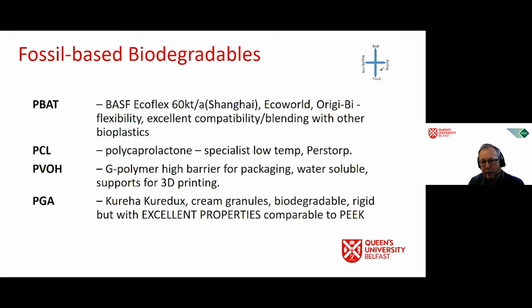So finally, of the four sections, if we look at the fossil-based biodegradables, this is where we use fossil-based materials to produce a biodegradable material. PBAT is probably one of the most well-known, and it is a well-established material. It is a very flexible material, which is used for flexible films, but it also has excellent compatibility with other biomaterials such as PLA, PHA, and thermoplastic starch. One of its typical applications is for compostable caddy bags. There are several suppliers of PBAT, and EcoFlex by BASF is just one of these, and they have a capacity of something like 60,000 tons per year.